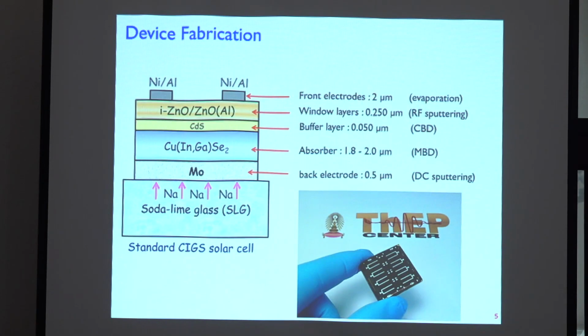Okay, the device fabrication has a multi-layer structure. The substrate is normal glass that you can see everywhere, like that you use for windows. This is known as soda lime glass. And molybdenum is used as a back contact. It's a metal. And CIGS is a photon absorber. The thickness is about 2 micron. That's very thin. Your hair is about 50 or 60 microns. So the thin layer of this material can absorb all the photons.